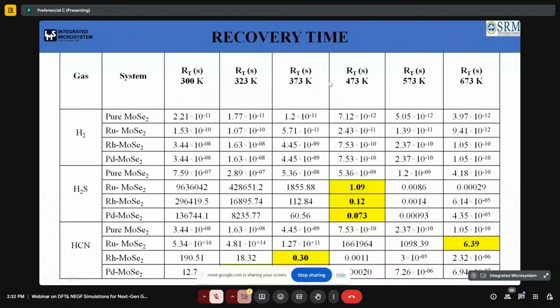We have done the recovery time analysis up to 673 Kelvin because the MoSe₂ monolayer is stable at more than 700 Kelvin, so based on that we did the analysis at high temperatures also. And when we come to HCN gas, for palladium we have observed a considerably good recovery time even at room temperature. But for ruthenium and rhodium, we have observed a good recovery time very close to room temperature, at a little bit larger temperature. So from this entire work, the main conclusion is as follows.